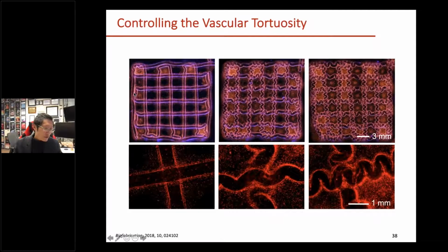And then by further tuning the bioprinting parameters, you can build in different variations. For example, in this case, we build in tortuosity or curvature into the hollow tube structures, right? Basically, if you mismatch the bioink delivery rate versus the nozzle moving speed, you can start to pack these fibers more and more and create more and more curvature into these fiber structures, allowing you to model some of the vascular diseases or other more convoluted hollow tissues in the human system.